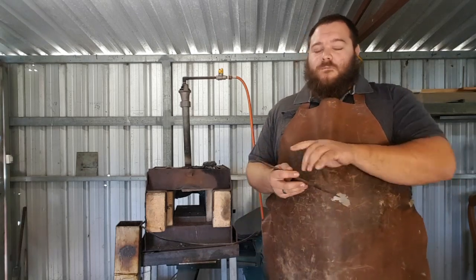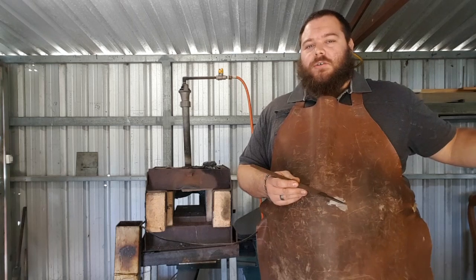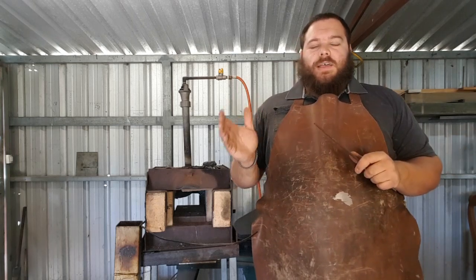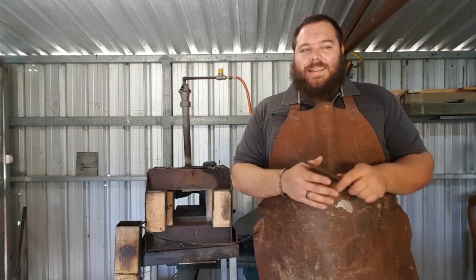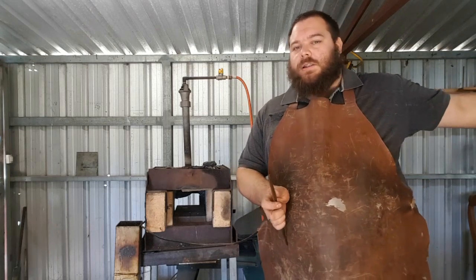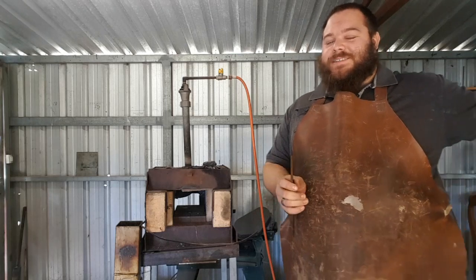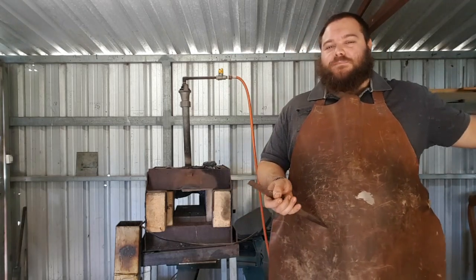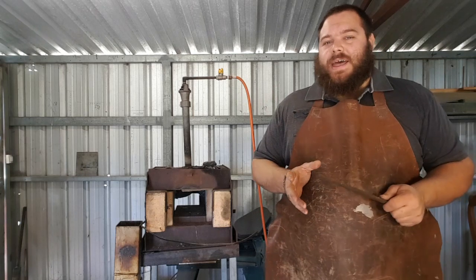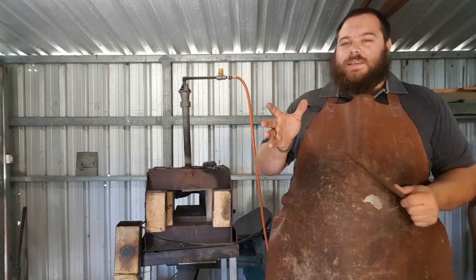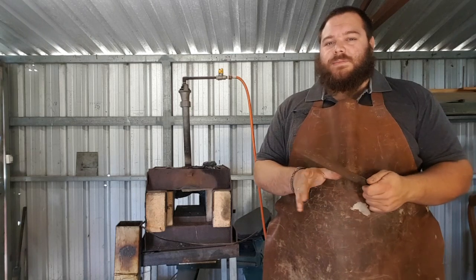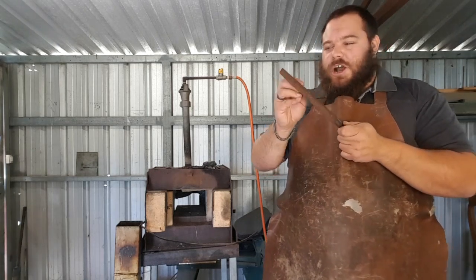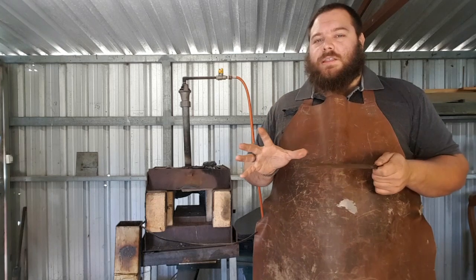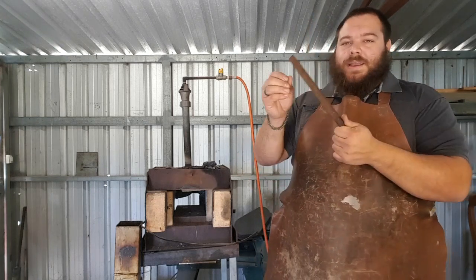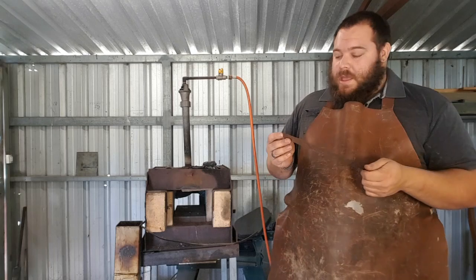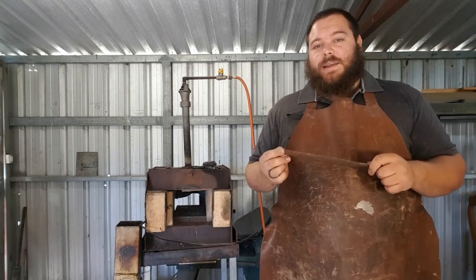And the problem with that is that they've way overshot the critical temperature, because a steel becomes non-magnetic at critical temperature and stays non-magnetic all the way up till it's a puddle of goo. You know, when it's a fizzing mass of sparklers, it's still non-magnetic. So the trick is to get it just to that point of non-magnetism. So, testing it constantly until it just won't touch the magnet, and then go a little bit further than that. Not taking it up to orange and going, yeah, magnet doesn't stick, and sticking it in your quenchant. But that is the important thing with magnet tests.